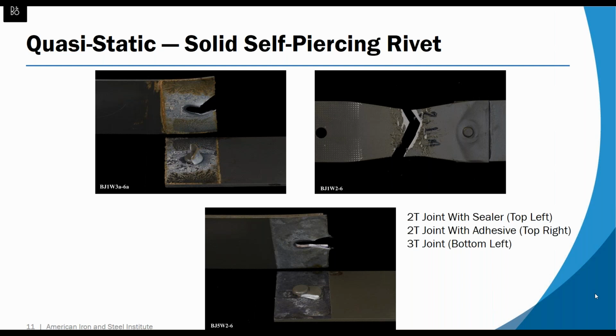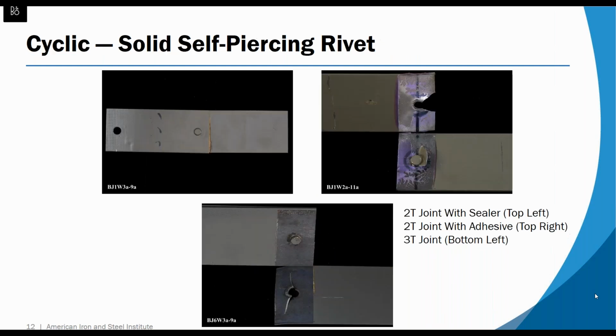In the upper left, it's a 2-thickness joint, but we have added a non-structural sealer to mitigate galvanic corrosion. And you can see the failure mode is very similar to the resistant spot weld. The top right is the same joint with a structural adhesive, and the failure mode, again, is in the top sheet. And the bottom is the 3-thickness joint without adhesive, and the failure mode pulls through the top 2 sheets more or less the way it did in the resistant spot weld.